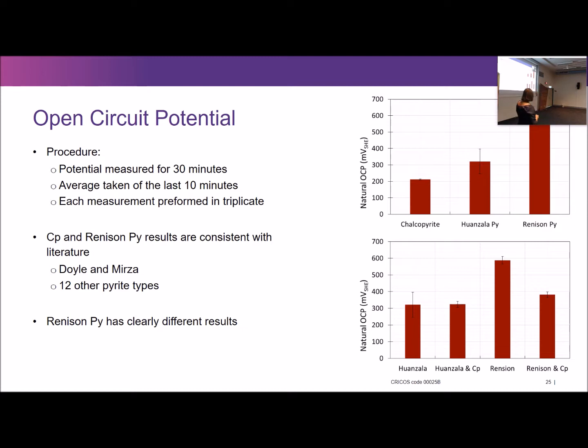So then when you look at the galvanic couples, this is Huanzala pyrite. When you couple it with chalcopyrite, its rest potential does not undergo a statistically significant change. So they're both within measurement error. However, when you couple Renison pyrite with chalcopyrite, it significantly shifts. So there is a much greater degree of interaction. So little interaction, a lot of interaction is the moral of this particular story.